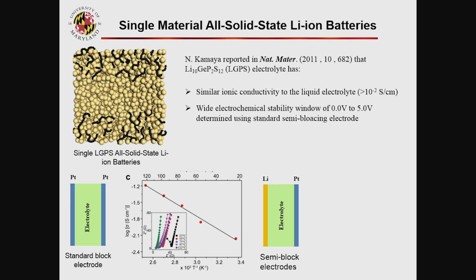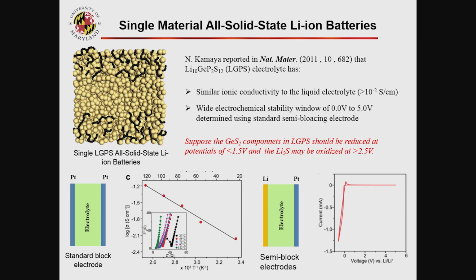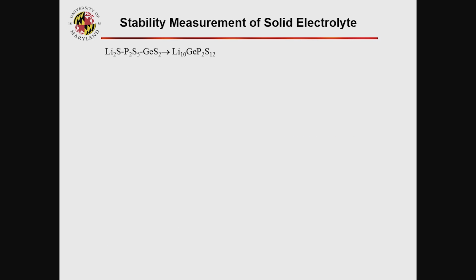We use the same setup: lithium, electrolyte, platinum, semi-blocking electrode. That is a standard method to measure the electrochemical stability window. We really get the curve same as the reported data. So it looks like what we are thinking is different from the result. And then we thought deeply, what happened? Why is there a difference? And then we check the difference. So the material, we say this is three materials mixed together, sintered. We got the new electrolyte. And then we got the window using the semi-blocking electrode.